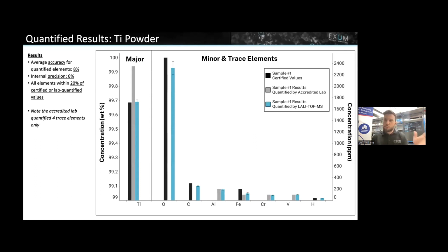The black is the certified value. So this is the value that came with this specific standard. And the gray was what was measured with an external lab for the same powder set. And Exum was within 8% for all quantified elements with an internal precision of 6%. And for a lot of elements, we were actually better than the external lab, kind of validating that, hey, we do get all the light elements and the heavy elements quantifiable within a few minutes of analysis here. Anybody can run.